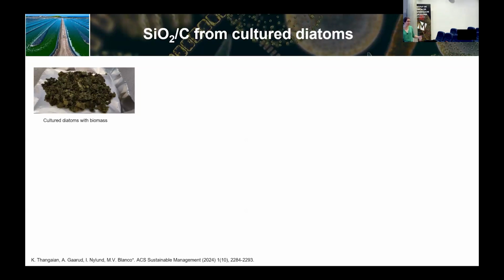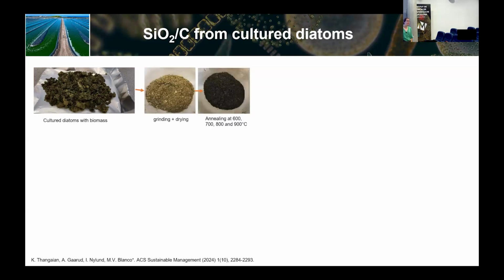So we tested just the bare silica just to compare it with the diatomaceous, but we also asked the company to ship us not just the skeletons of the algae, but the algae with the biomass, because in nature, the algae is growing the biomass, and the biomass is attached to the skeletons. So we asked them just to send us just the diatoms without any major procedure. So they did some simple washing with DI water just to get rid of some salts, and then they ship us just the diatoms with the biomass. So we did some grinding and drying, some annealing at different temperatures just to try to coat the material with the biomass that was also part of the algae.